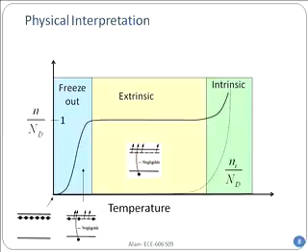Now if you increase the temperature even more, the donors have given whatever they could. Remember, in the valence band, the effective density of states is on the order of 10 to the power 20. Lots of states, lots of electrons. So when you increase the temperature, if electrons can make the whole jump, they can give a huge number, much higher than what donors can give.